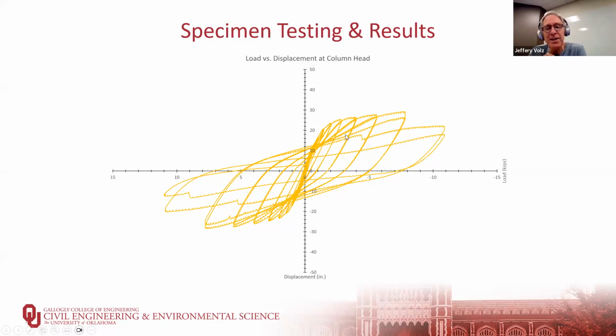It's fairly stable initially, but then at some point you get this little dip here and these dips here. What happens here is because of the high strains, we most likely either buckled a bar or fractured a bar due to the strains getting too high. And that's why there's a dip in capacity, but there are 8 bars in there and the other bars start picking up the load and we get a continual hysteresis loop, but at a much lower load. So much lower in terms of the lateral load, also much lower in terms of the energy absorption. And this is very common of a reinforced concrete column tested in this type of protocol.